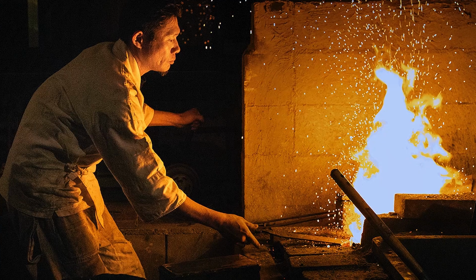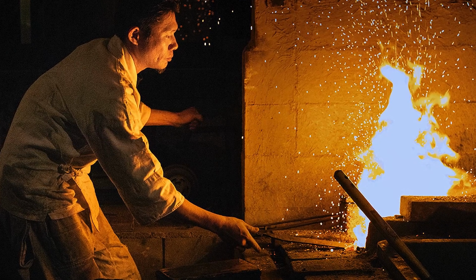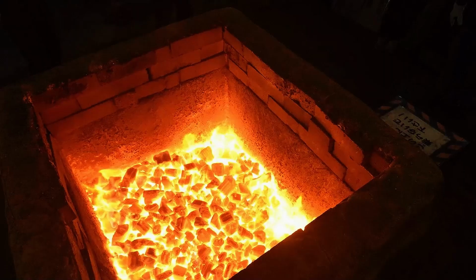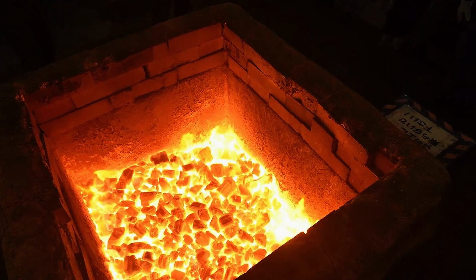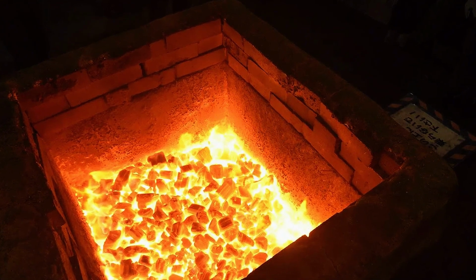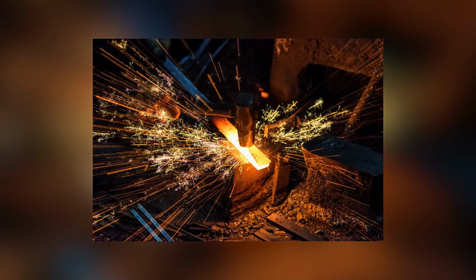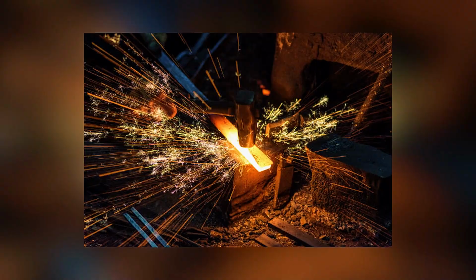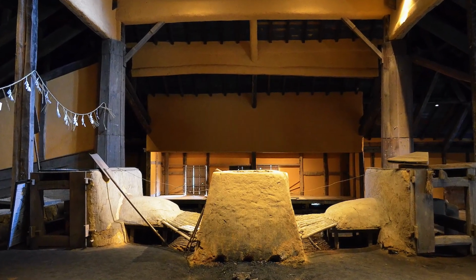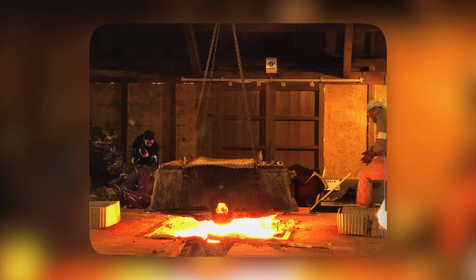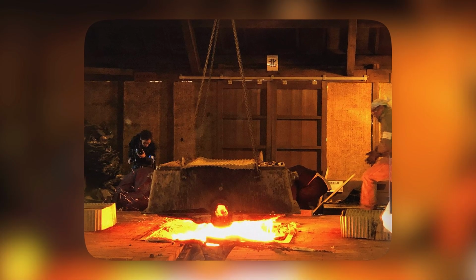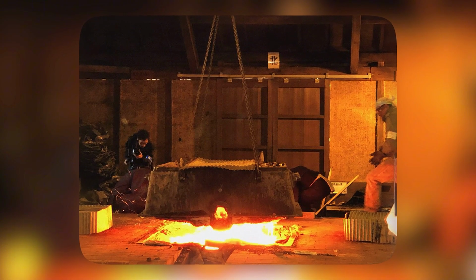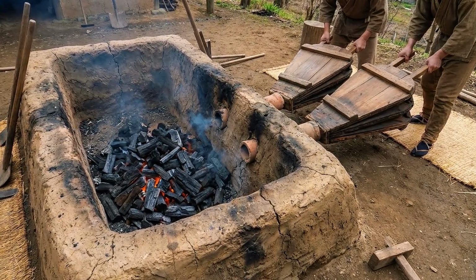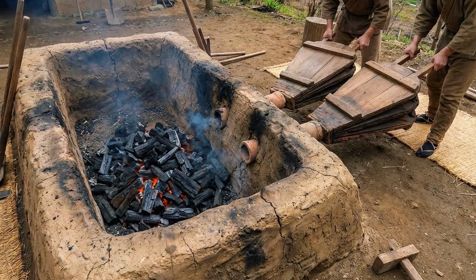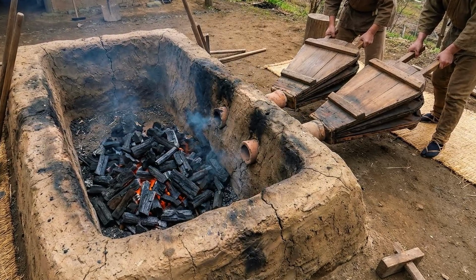Carbon monoxide from burning charcoal steals oxygen atoms from the iron oxide. The genius of the tatara is that it operates where iron stays solid, but impurities melt. Iron particles sinter together, forming a spongy bloom. Silicon oxides, sulfur, phosphorus flow to the bottom as liquid slag. Over 72 hours, a typical tatara consumes 8,000 kilograms of charcoal and 1,200 kilograms of iron sand. At the end, the furnace is disassembled. What remains is a 2.5-ton block with 800 to 900 kilograms of tamahagane, jewel steel, buried inside.